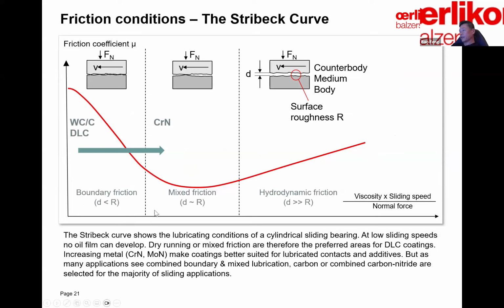The Y is the friction coefficient, and the X is the lambda ratio, which describes the lubrication conditions. On the left side, you have asperity contact, high pressure, low speed. You squeeze the lubrication film completely out. You will rely on the DLC type of coating to provide the lubricity. And as you move to the right, you come to the mixed lubrication regime, where you do have a little bit of lubrication, but at the same time you still have asperity contact. That's where that special chrome nitride coating will work best.